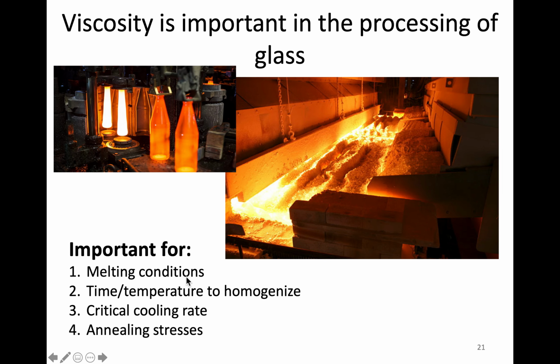It's important for the melting conditions. Starting with the raw ore, how do we melt that and then make that into a formable material? It also matters for the time and temperature to homogenize, basically getting everything the same. It's going to matter for what we call a critical cooling rate, the separation between a crystalline material and an amorphous one. How quickly do we have to cool to get that amorphous material? If you have to cool extremely rapidly, then that's not a practical material to make in real life.